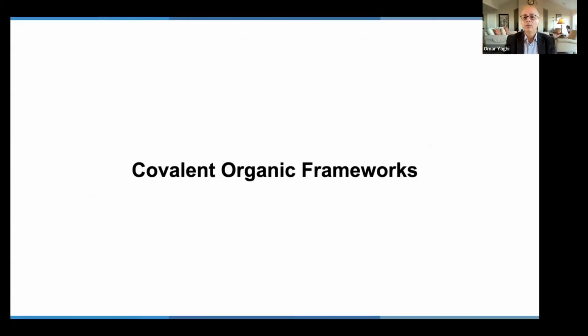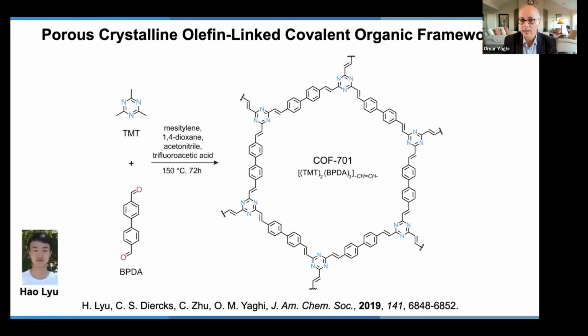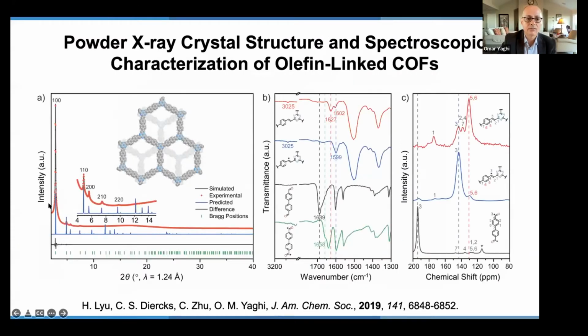So I won't go through what we have done in covalent organic frameworks, but just show you the latest results on one covalent organic framework. Now, these contain no metals. The backbone is entirely organic, and you can see here that this structure is made entirely of carbon-carbon linkages or olefin linkages, and that this can be crystallized and made. And this shows the X-ray powder diffraction with very sharp lines for the structure.